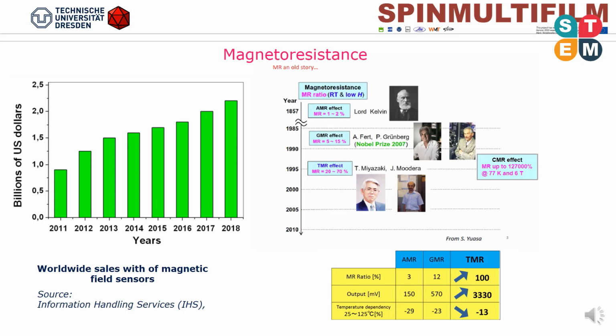Magnetoresistance is a property of a material to change the value of its electrical resistance when an external magnetic field is applied. The magnetoresistive effects in materials are classified into several categories according to their driving mechanism, namely the anisotropic magnetoresistance AMR, first observed by Lord Kelvin in 1857 in nickel and iron. The giant magnetoresistance GMR, a quantum mechanical magnetoresistance effect observed in multilayers composed of alternating ferromagnetic and non-magnetic conductive layers, awarded the Nobel Prize to Albert Fert and Peter Grünberg in 2007.